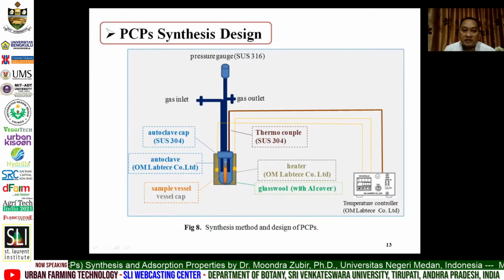This is the PCP synthesis design outside the magnetic field, so no magnetic field is used for this synthesis. All the metal ion and the two ligands are mixed in this sample vessel with a vessel cap, then inserted into the autoclave system and left for 12 hours.